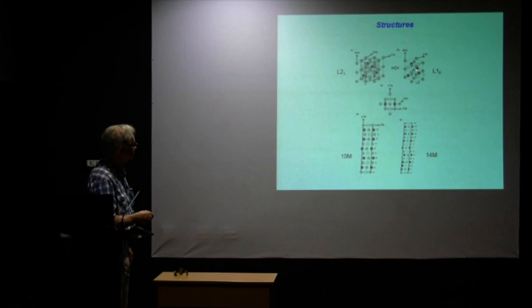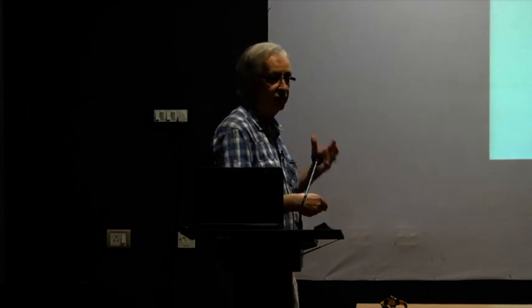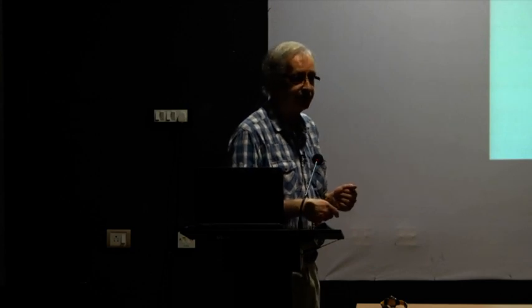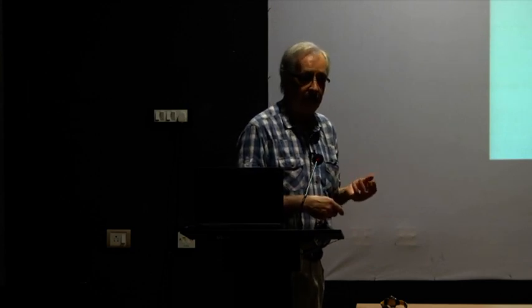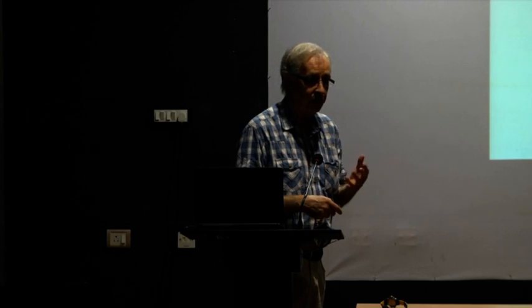Now, if we look at this from the top over here, we have these gray atoms sitting over here. And then a little bit below, we can see these two black atoms. And then we should be able to see these two white atoms over here, when we're looking from the top of these things. So this is the pure L10 state, but in very many cases, we observe modulated structures in these alloys.